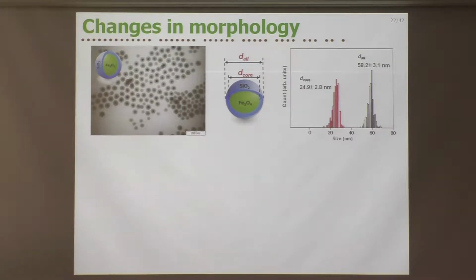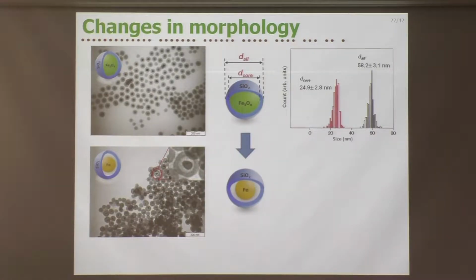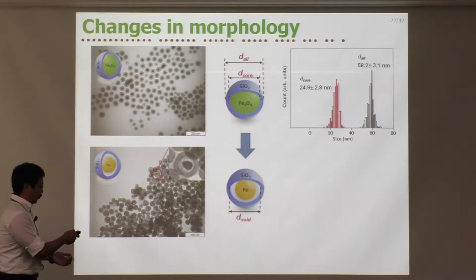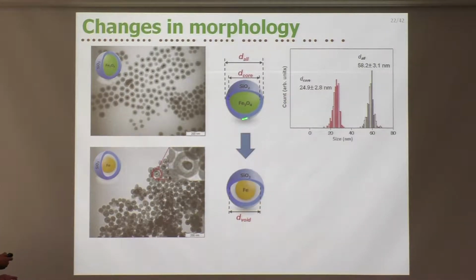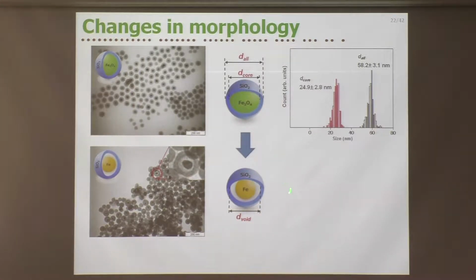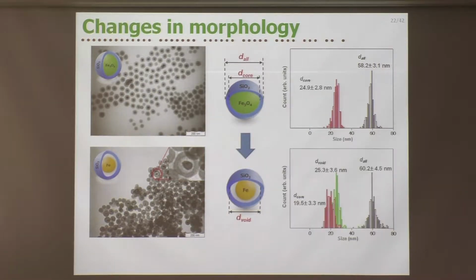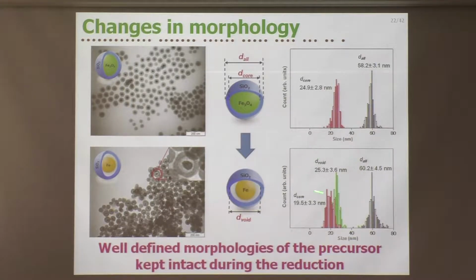We carried out the reduction. Here again is the same TEM image after reduction. Now we have a new characteristic size: the size of the void. As I explained in the previous slide, this void formed because of the volume shrinkage during reduction. So the size of the void is expected to be the same as the size of the core before reduction. How about the results? Here shows the size of the void.